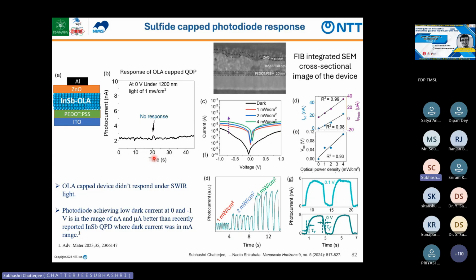By making that at 0 voltage, we can see the photocurrent was generated, though the speed was unfortunately very low. But the main important point was that at 0 voltage the photocurrent was achieved. If we change the incident light, we can get very nice features of the photodiode.